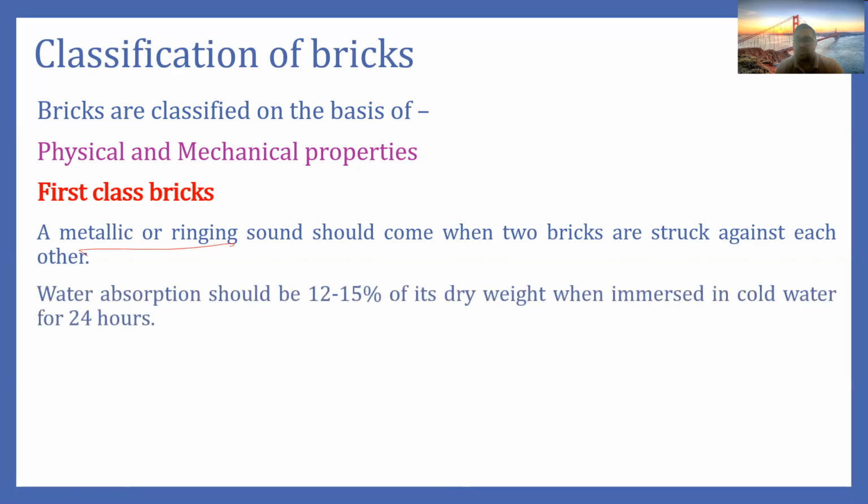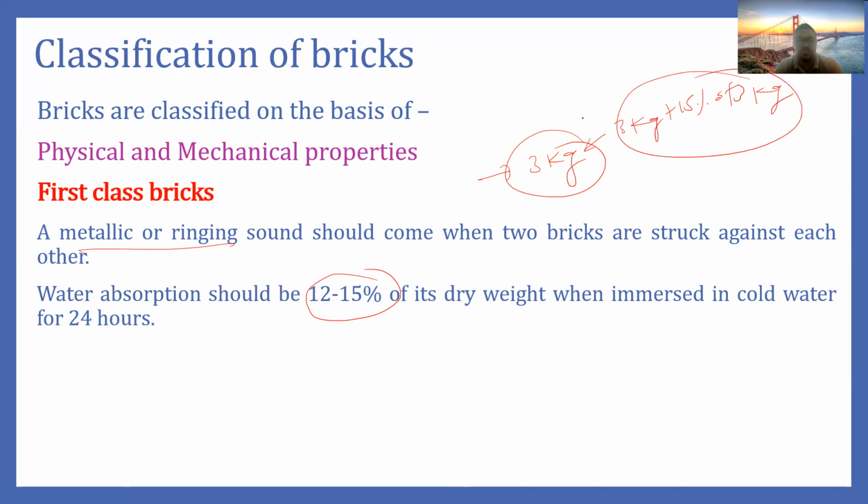The next is water absorption. When we keep the brick in the water for 24 hours, the total water absorption should not be more than 15% of its dry weight. So for example, if the weight of the brick is 3 kg, the total weight after 24 hours of cold water immersion should be 3 kg plus 15% of 3 kg. It should not be more than this.